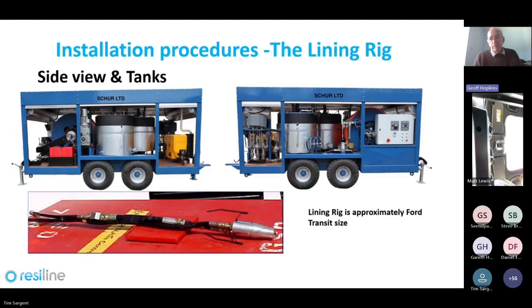On the upper right-hand picture, the other side of the lining rig, at the left-hand end of the rig, you can see the metering pump. So that has three legs on it, so it's fixed ratio delivery. So there are generally two base pump legs and one activator pump leg. So that's fixed ratio displacement of material at the correct mix ratio. Next to the tanks, the material runs through flow meters, and from the flow meters it then runs through a central coupling into the hose drum, which is inside at the right hand end of the rig.